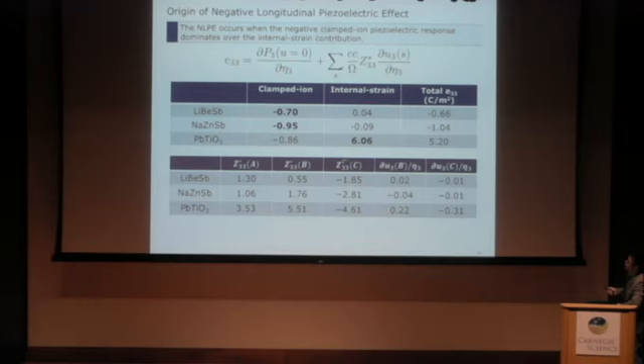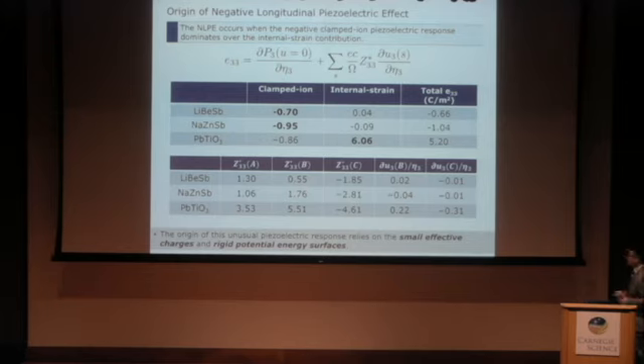The origin of this negative response really comes from this negative clamped-ion term. As you can see from the table, for these two compounds, they have negative clamped-ion terms, the same as PbTiO3, but they have a very small, nearly zero internal strain term. However, in PbTiO3, this internal strain term dominates. Because of this very small internal strain term, these two ABC ferroelectrics have negative e33. We also look at the Born effective charges and the atomic relaxation in response to the macroscopic strain. As expected, these ABC ferroelectrics have pretty small Born effective charges, and the atoms don't move that much in response to the external strain. So it's very clear to us now that the origin of this unusual piezoelectric response relies on the small effective charges and also the rigid potential energy surface.